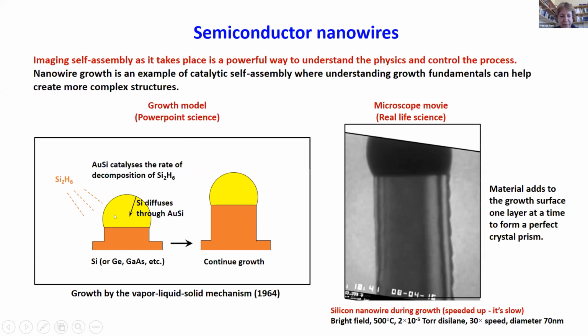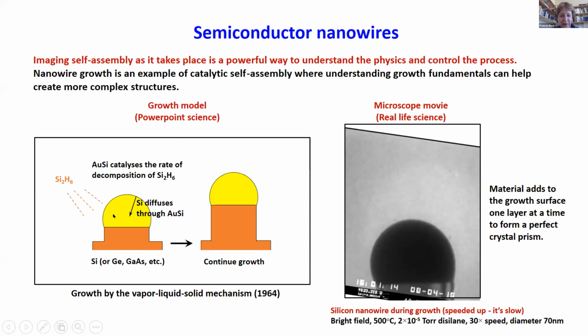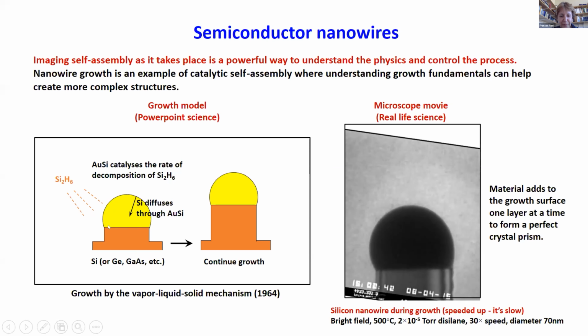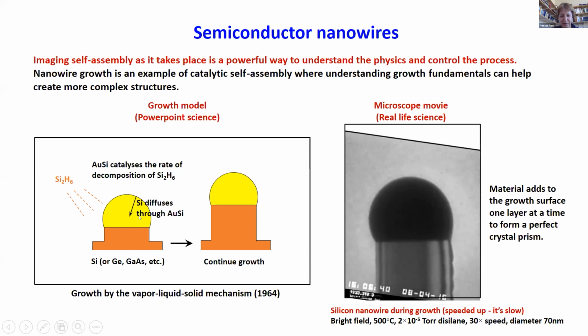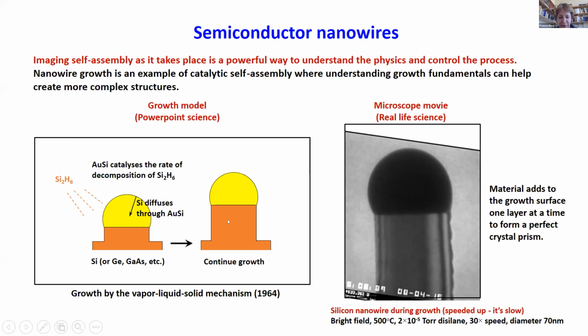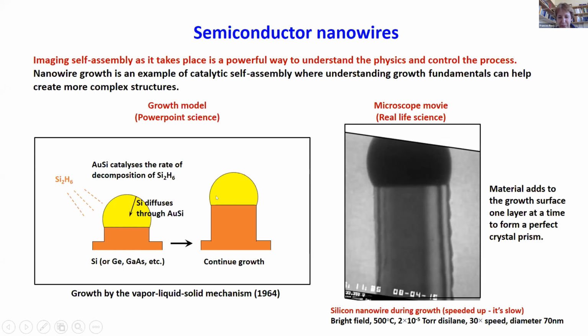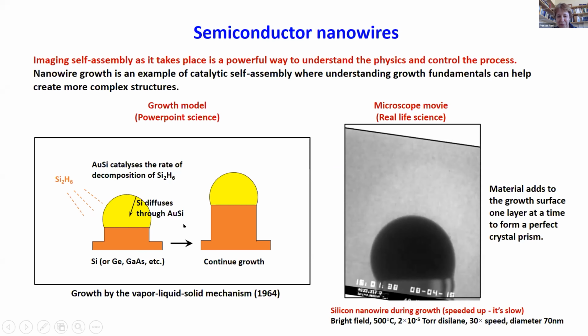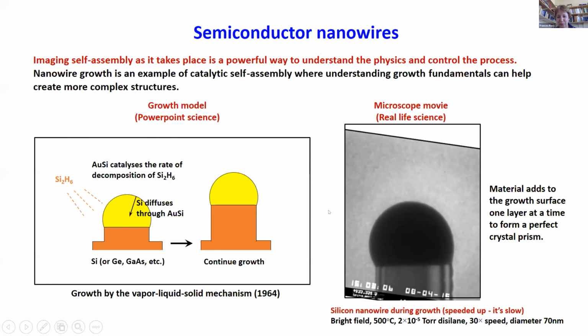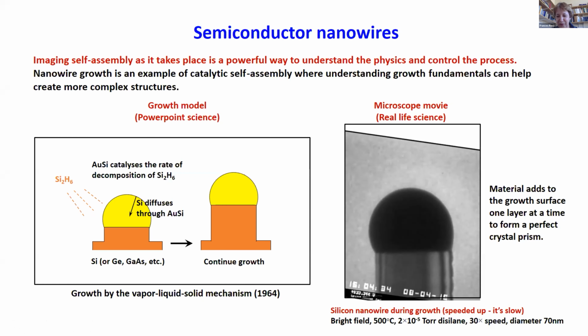The gas decomposes, the silicon is left behind, and it attaches much more readily on the surface of the droplet. And so you get a supersaturation of silicon within the droplet that gets precipitated at the interface and therefore adds silicon layer by layer at the growth interface, forming a nanowire that just keeps growing and carrying its catalyst along with it. And this model was proposed in the 60s, but here we can verify it in the electron microscope and show that in fact the PowerPoint science really does express what's going on pretty accurately.